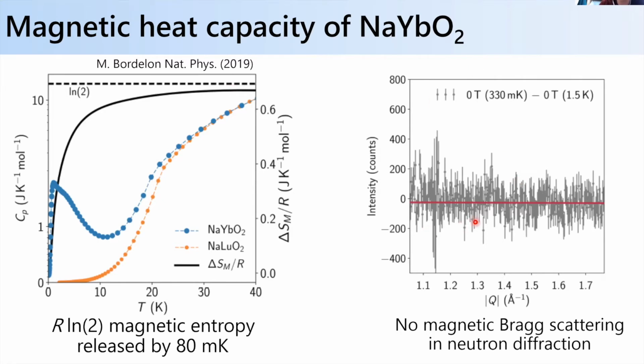Okay, and just as confirmation, we can do neutron diffraction on the material. I'm just showing you temperature subtracted data here, showing as we cool the system down, in this case down to 300 millikelvin. We have other data showing down to 50 millikelvin. You don't see any magnetic Bragg peaks, or any correlated magnetic scattering up here. So this is just showing you that the system does not magnetically order as far as we can tell.